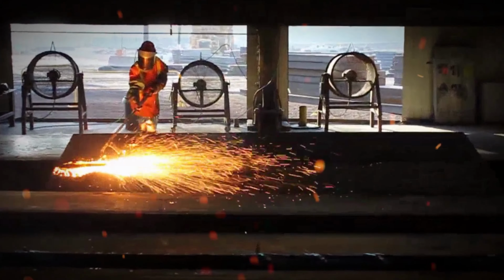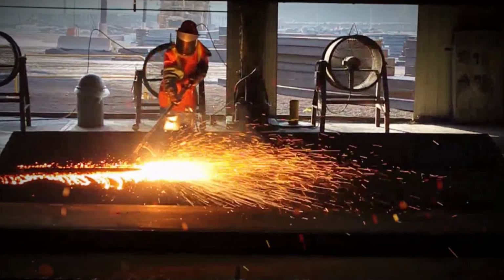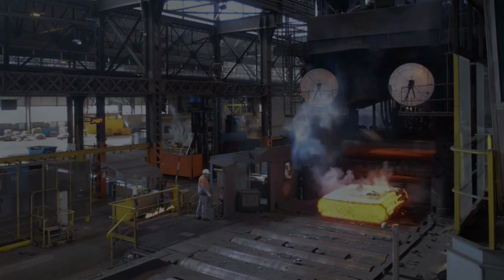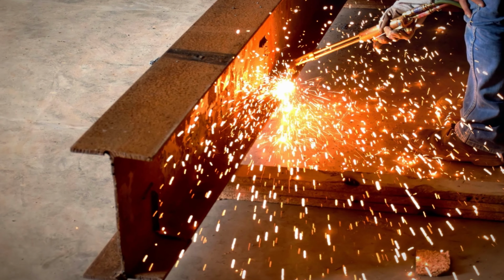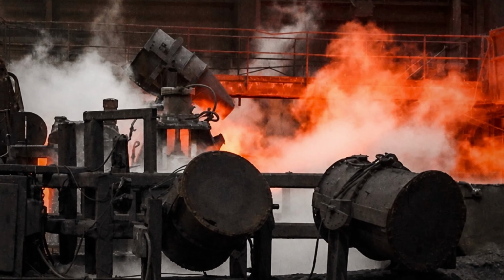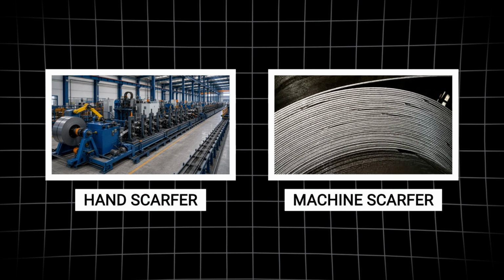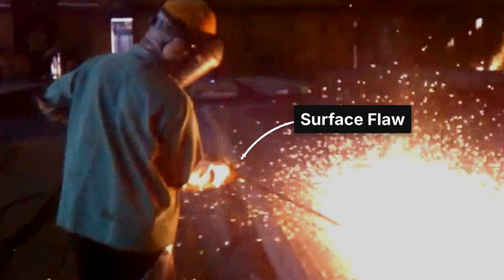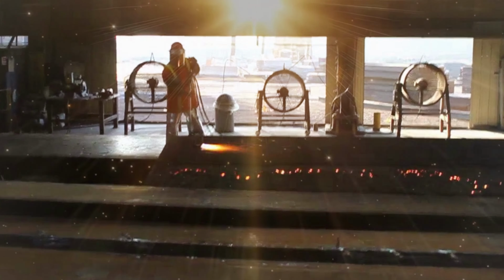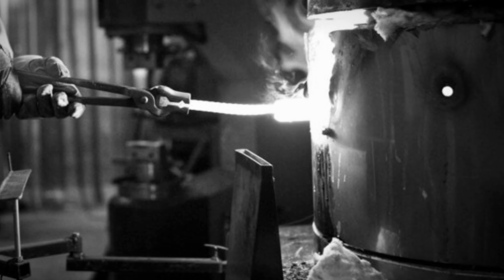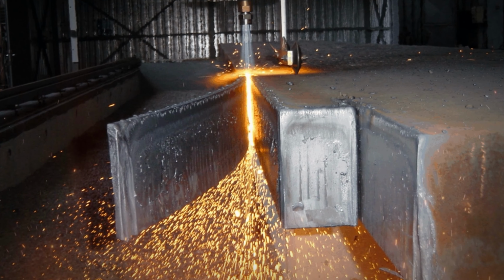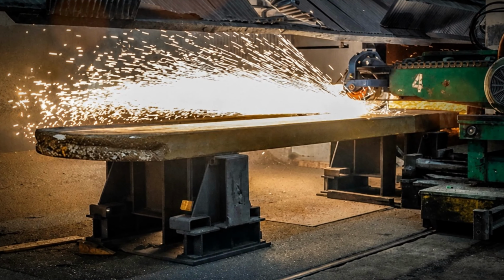He judged depth by the color of the burn and the behavior of the sparks, crouched over metal still hot from the pits, in leather that smoked. It was brutal, dirty, low-glory work, and it required the fine motor control of an engraver. Machine scarfers exist, great automated flame boxes that burn the entire surface of a slab as it passes. They work by removing everything, good steel and bad, because the machine cannot tell the difference. The hand scarfer removed only the flaw. One process is surgery, the other is amputation. Guess which one we kept?